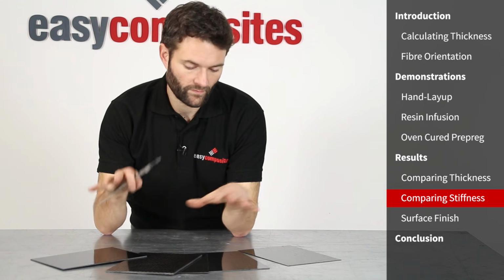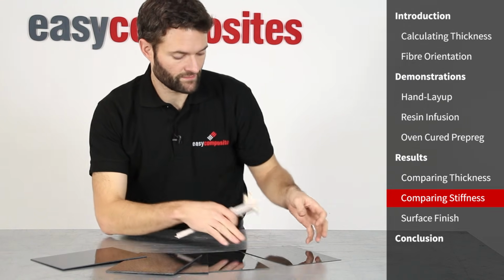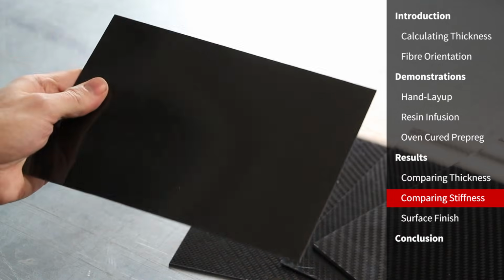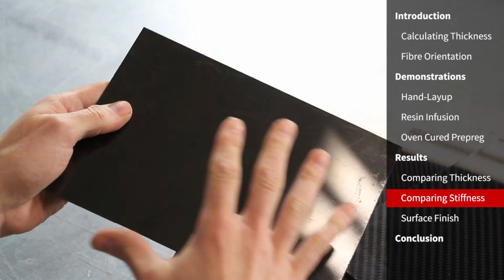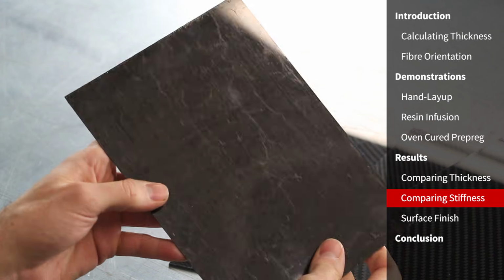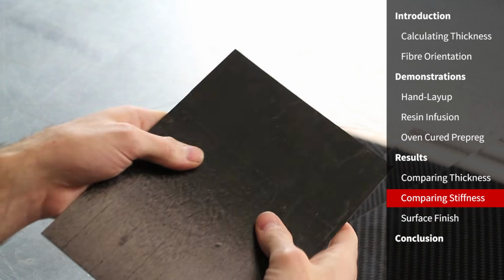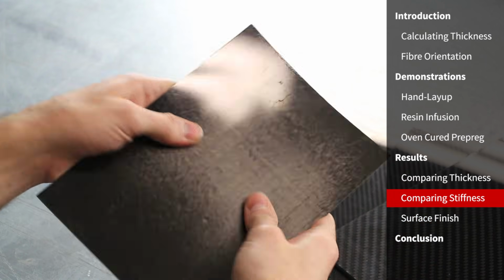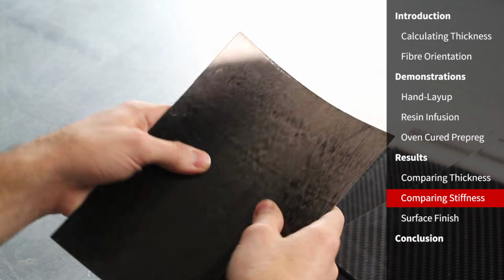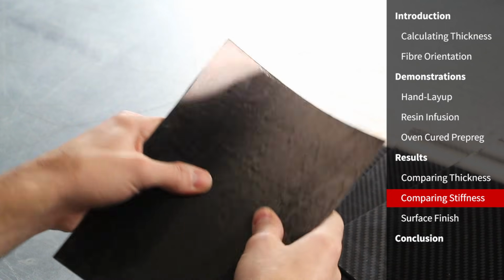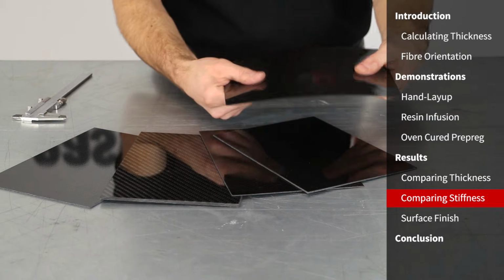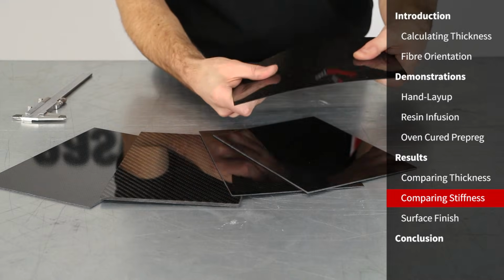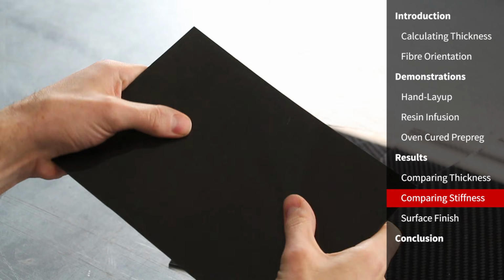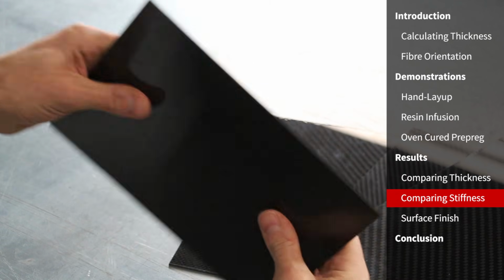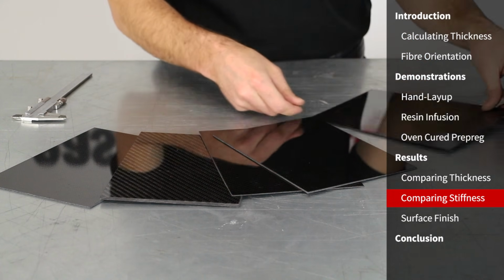Another thing we looked at when we made these sheets was fibre orientation. Probably the most pronounced impact of fibre orientation was the unidirectional sheet. So in this direction, extremely flexible. In fact, I could certainly flex this and snap it in that direction. But in the direction where we have the strength, where all of the fibres are running lengthways down it, then extremely strong, certainly for its thickness, in that direction.